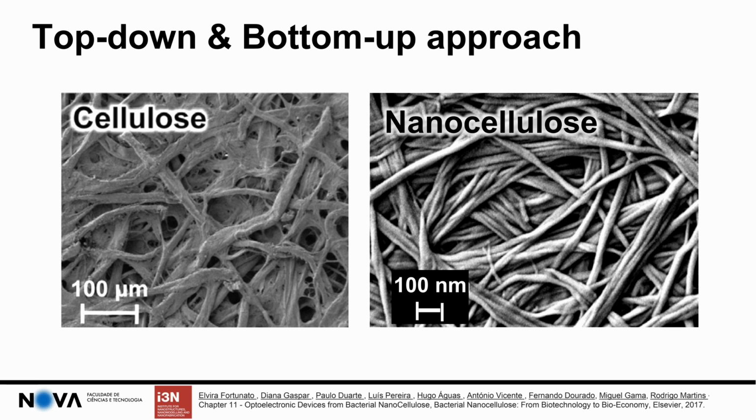And again, for example, if we compare the vegetal cellulose with the bacterial cellulose, in these two images from scanning electron microscope, on the left we have vegetal cellulose, and on the right we have the nanofibers, cellulose with origin in the bacteria. But if you take a look at these figures, they are quite similar. We have a 3D random orientation of these fibers.